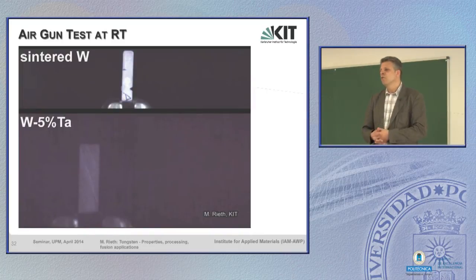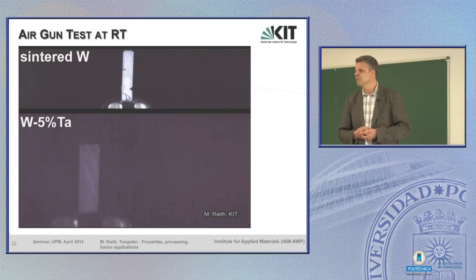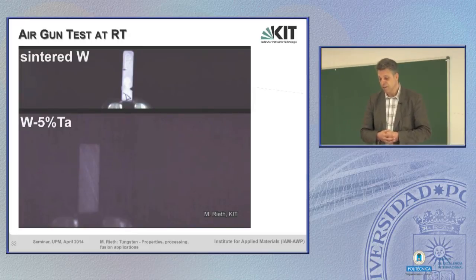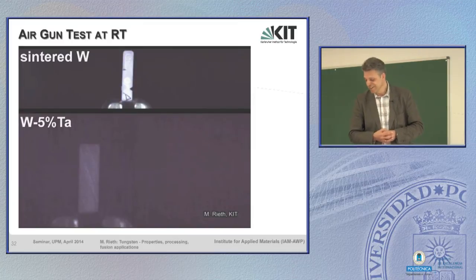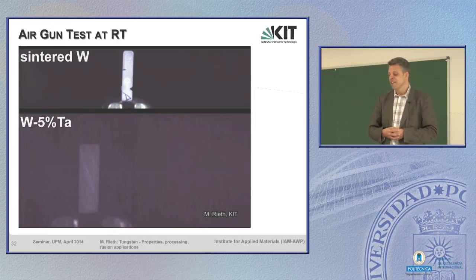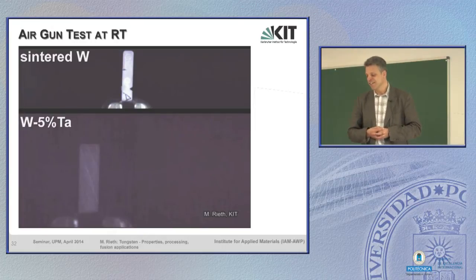And now, to really visualize the brittleness and problem with tungsten, there is just another, let's say, funny test which we have invented, or, well, you know, scientists also like to play around a little bit. That's the so-called air gun test. We used an air gun and shot it on a Charpy specimen sample out of sintered tungsten, and here on a rather big or thick plate of tungsten 5% tantalum, and look what happens.